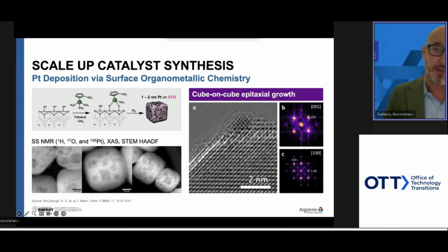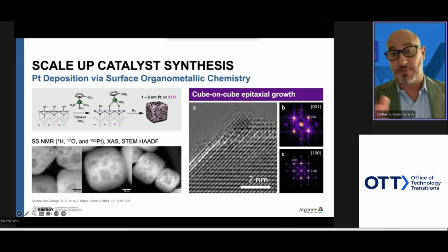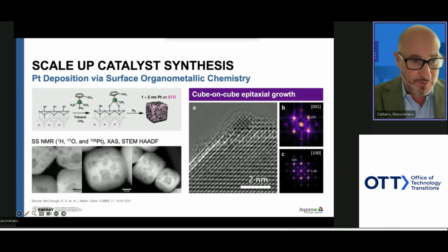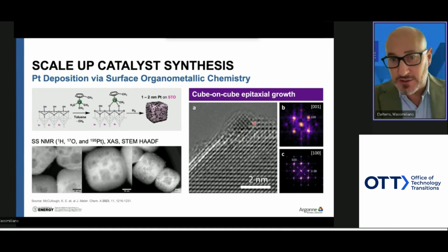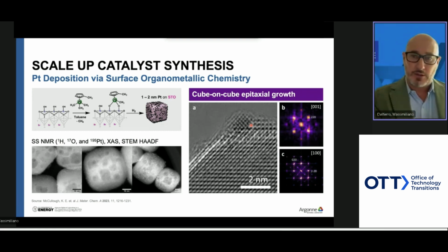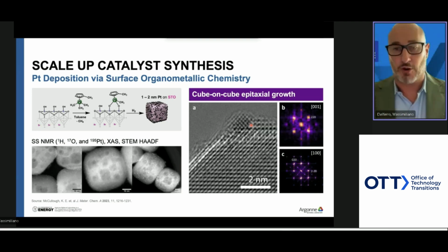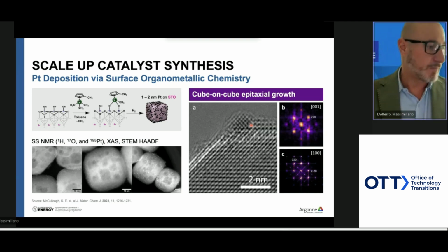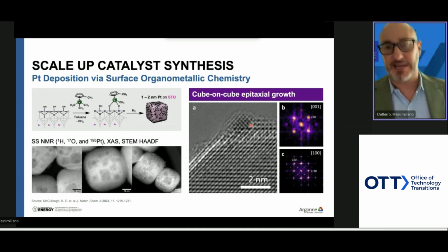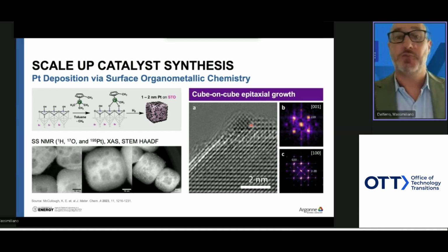the deposition of the metal. And we show, for example, in this beautiful image of the cube-on-cube epitaxy, if you're interested in the chemistry, this is the platinum nanoparticles, and this is the support, and we have this beautiful cube-on-cube epitaxy that stabilizes the platinum also when we start to make kilograms of this material, meaning we are not losing the properties from the lab to the pilot plant, or the average amount of catalyst that's needed for some pilot plant experiments.